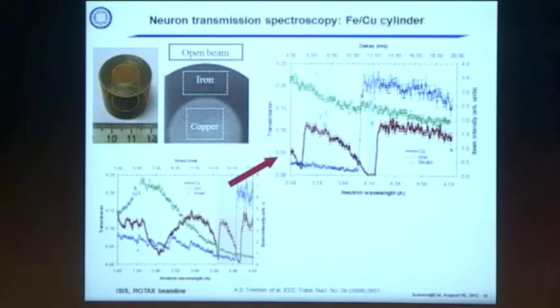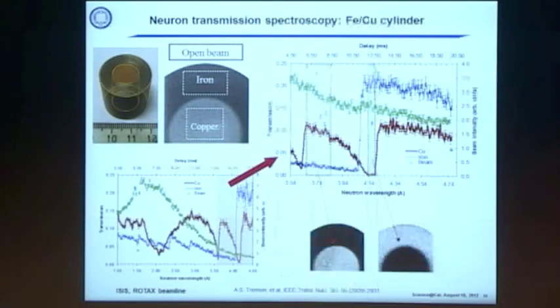And if you look in the area of one, the gray area highlighted in this graph, the iron is not absorbing much, but copper is absorbing. And in area two, it's vice versa. Iron is absorbing, copper is not. So what you can do now, you can get the same object, but the image is black and white, white and black. So just having energy resolved imaging, you can do material dependent studies, see where different materials are,